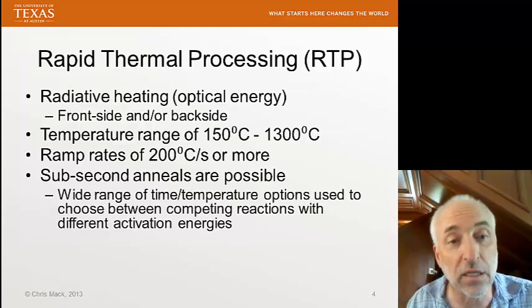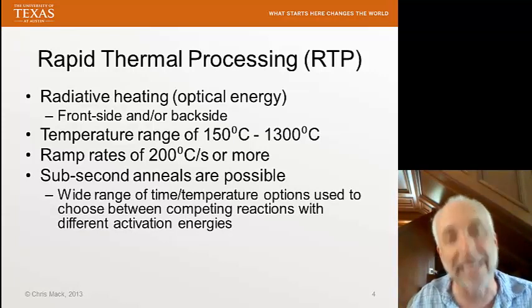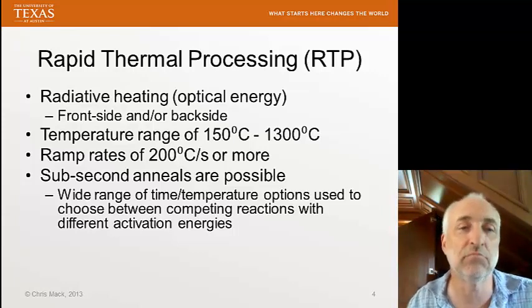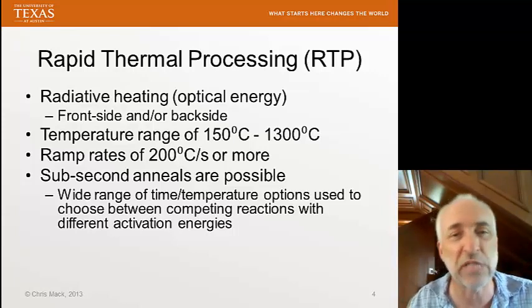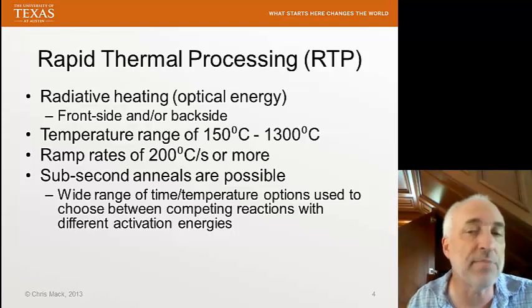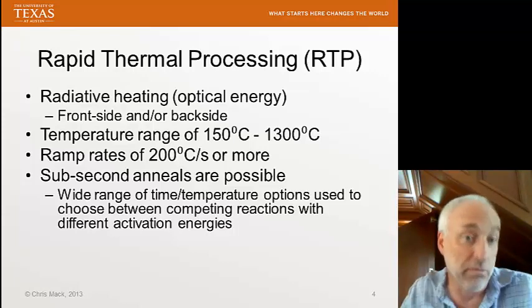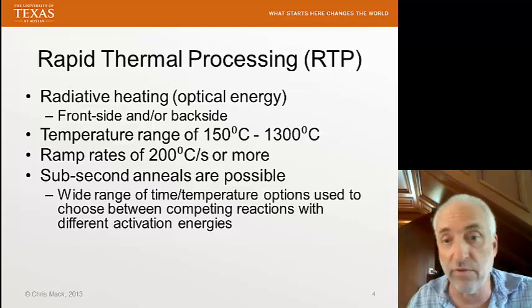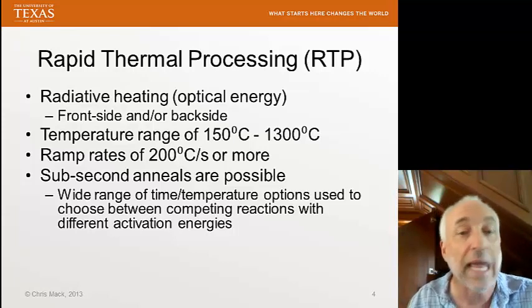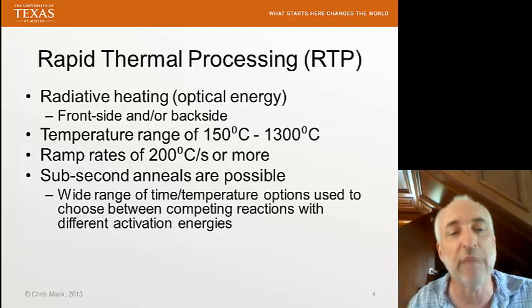We can control the time at the highest temperature to less than a second. Typical short anneals are in the 1 to 2 second regime, but it is possible to go even shorter. This gives us a wide range of time-temperature options — we can keep it in longer for a longer soak if we'd like, so we have a huge range of temperatures and times including very short times.